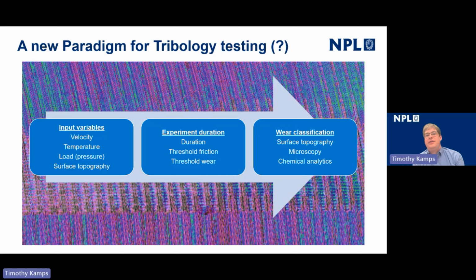So conventionally, once the interface has been analysed to extract the contact kinematics, we would then look to match that in the tribometer. So typical input variables might be velocity, global temperature of the contact, the load, and also the surface topography of the contacts. And then we might be looking to set the duration either as a cumulative energy dissipation duration. So this might be realized as a sliding distance or just as a time duration.